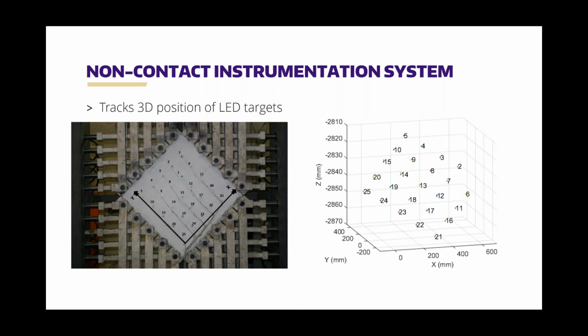I'm basically just going through the process here since the data is still coming in, but just to give you a sense for what we're doing and why we're doing it, and for this type of research. We're tracking the position of the panel, the deformations within the panel, using these LED targets. Again, we're applying some known state of stress. We're measuring the state of strain, so we're able to then use that to develop these behavior models.